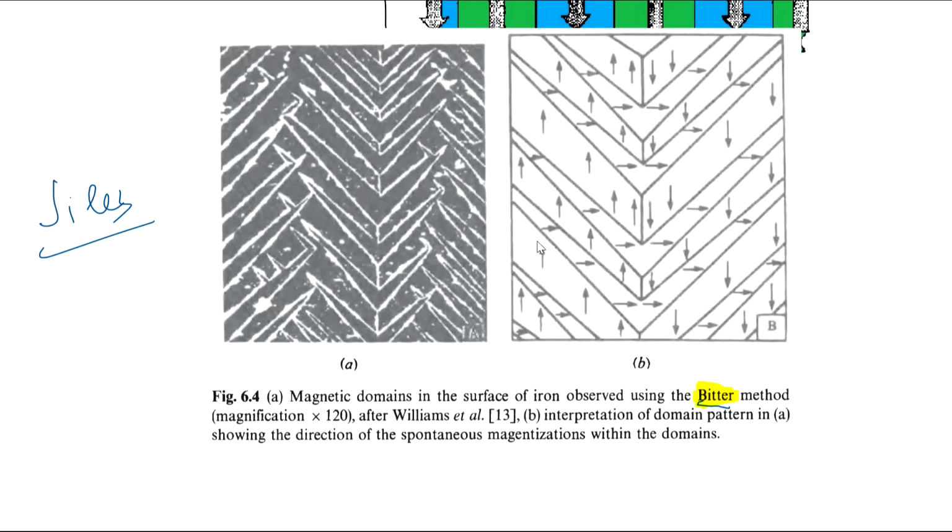So you can see that this is an image where white indicates the powder. White indicates where the magnetic powder particles locate themselves. And these white lines on the dark background are basically the shape of the magnetic domains. So you can see it under a regular microscope. And then this information about the domain shape can be used to extract the magnetization alignment.